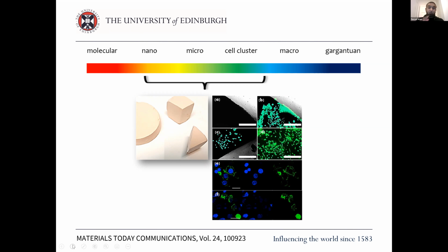And what we found is that they preferred to grow on these diatom-based architectures than they did on Sigma-Aldrich Nunc plates, which are specifically designed for cell growth. And they grew with perfect morphologies. There was no unhealthiness. If you look at the HEK cells and the pre-osteoblasts and the breast cancer cells in this image, you can see that they have shapes that are typical for those cells.